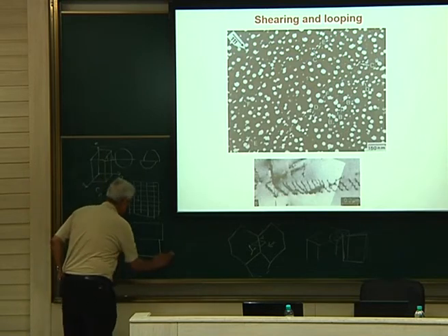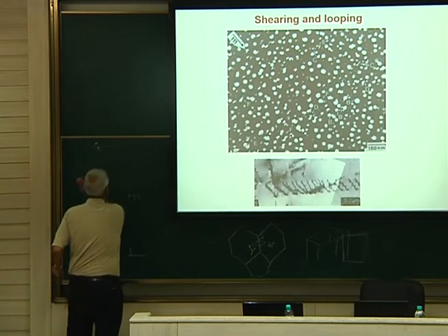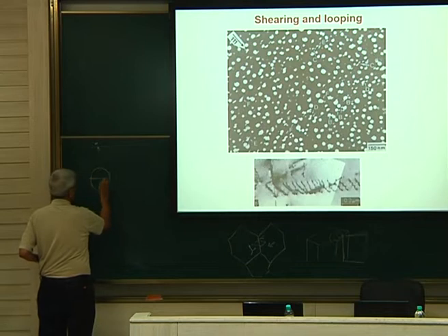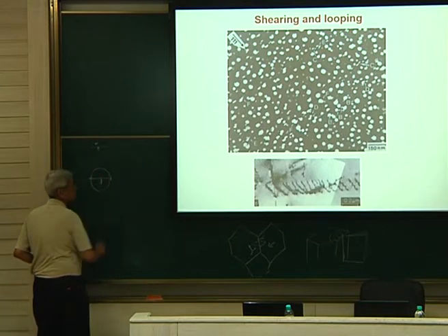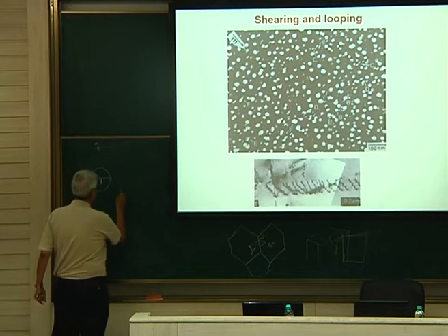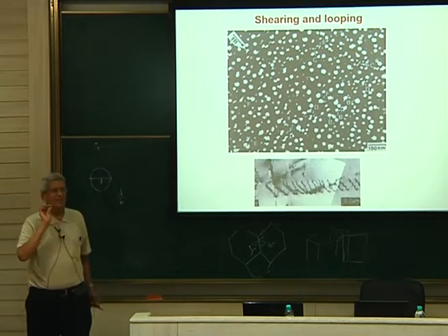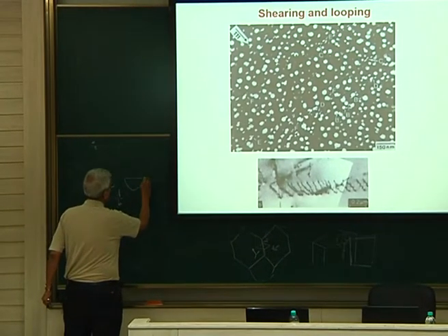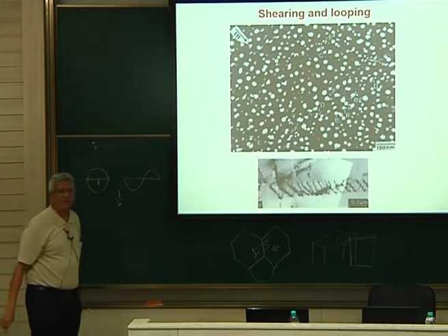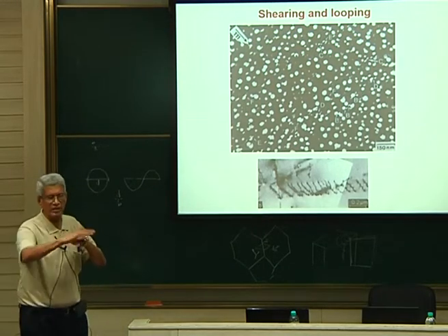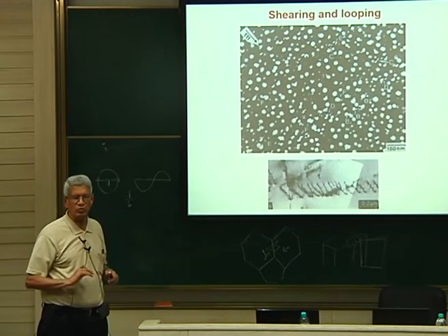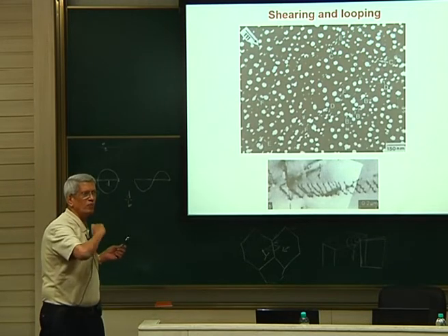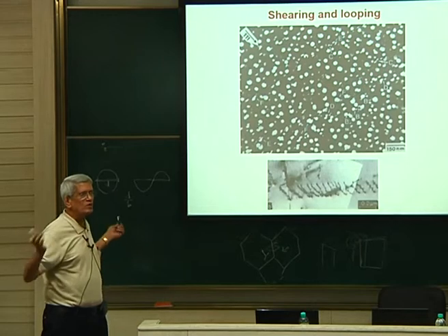It's a shear, this is to do with the particle size. That is, if I see a particle of this particular size in the slip line, I know this is the distance d. If I know b, d by b will give you how many dislocations should have passed through to separate this into two separate halves, correct? Once in the slip plane it has already separated, when the next dislocation passes through, it doesn't see the ordering at all in that slip plane. So it will be essentially like a perfect matrix dislocation passing through. Then you will not see the group of dislocations.